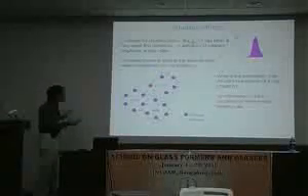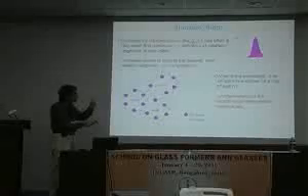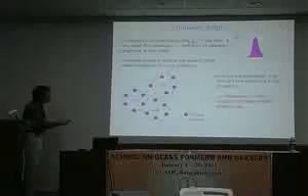Now, if you want to go on even a slightly larger level, then you can look at, for certain systems at least, the so-called ring statistics. So again, you use the g of r to define what is a nearest neighbor. So the nearest neighbors are all the atoms that have a distance from the atom sitting at the origin that is smaller than the location of this first minimum here. And so if you have a network-forming system like silica or sodium silicate, then, well, this is just a cartoon, but basically you have, let's say here in pink, the silicon atom, and in light blue the oxygen atoms, and basically you can make this loop-like structure.